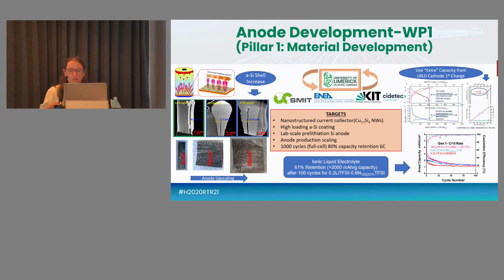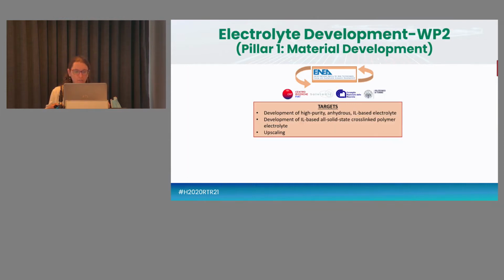The target for the anode side is 1000 cycles in a full cell configuration with 80% capacity retention at 6C. Here I'm showing just the preliminary results that were fundamental for identifying the best composition of the ionic liquid electrolyte, which demonstrated to be the most promising one regarding the anode side.